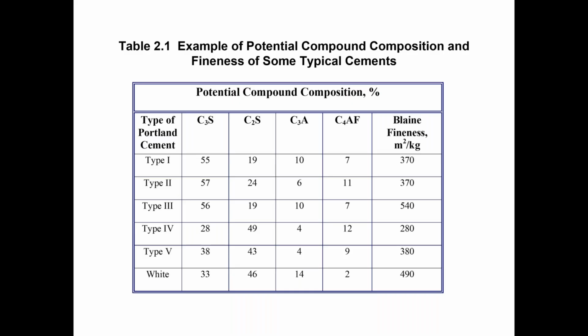Notice that for white cement, that C3A is pretty high percentage, 14%. So what that means is that white cement may have a higher potential for sulfate attack than most gray types of cement. So this is one of the reasons why you're not going to see white cement used in any environment where exposure to sulfates or other chemicals is going to be likely. You're not going to see any white wastewater treatment plants because of the high C3A content and the higher potential for sulfate attack.